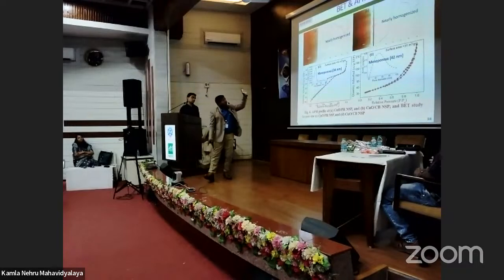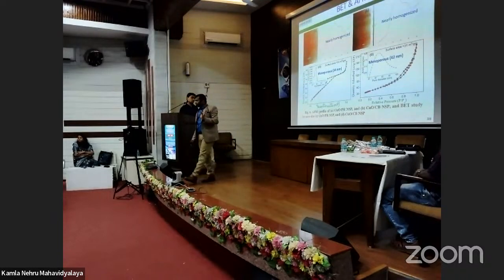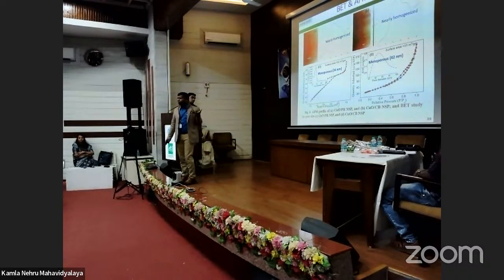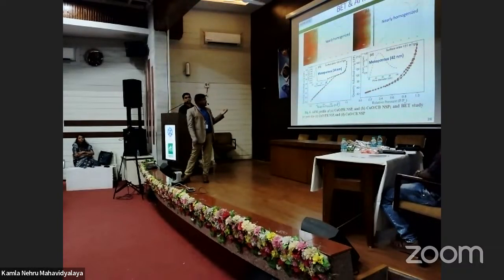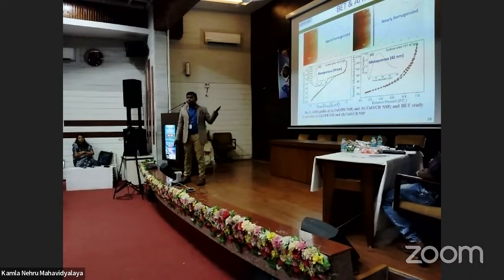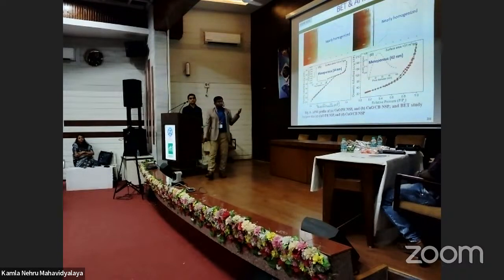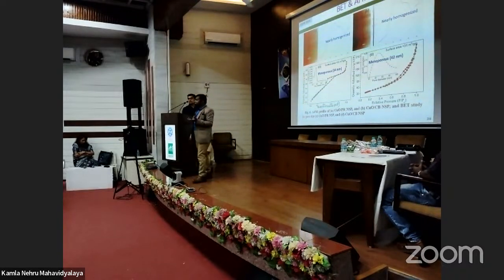So that can reveal that it is nearly homogenized, and the base surface reveals the mesoporous nature, and why mesoporous, because of 34 nanometer as well as 42 nanometer, and the surface area is also good. Surface area is 22 meter square per gram. Next,